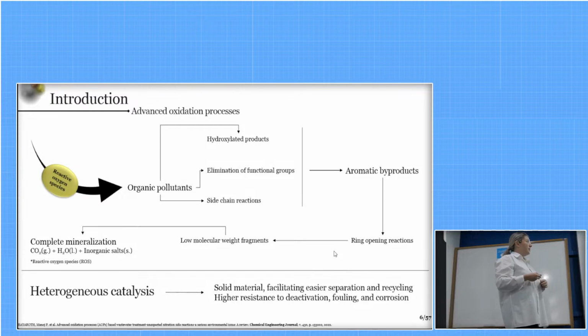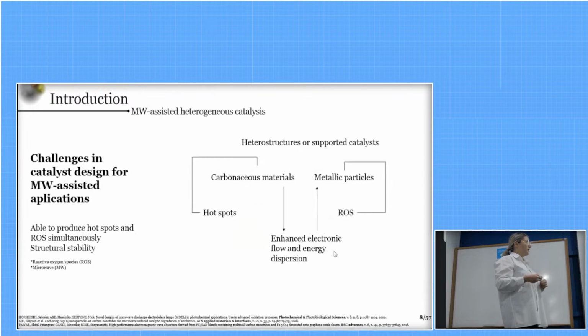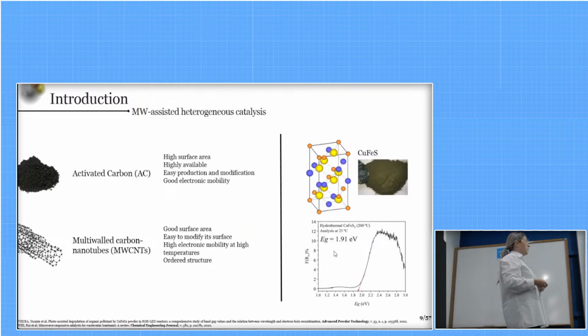The literature then suggests the use of heterostructure or supported catalysts, such as the use of carbonaceous materials for producing hotspots or metallic particles to promote the reactive oxygen species. The combination of these two materials is proposed to enhance electronic flow and energy dispersion, optimizing the use of microwaves. Here we suggest the use of activated carbon because activated carbon has high surface area, it is highly available, easy to produce and modify, and it has good electronic mobility.